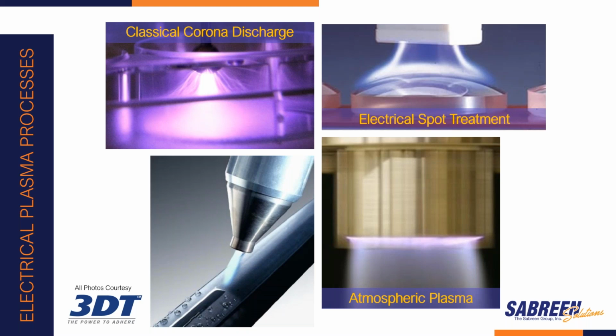Next, on electrical air plasma, it's a corona discharge spot treatment. In this method, the head consists of two hook electrodes in close proximity to each other connected to a high voltage transformer generating an electric arc of approximately 7 to 12 kV, but at lower frequency, 50 to 60 cycles. Then, using forced air, a continuous electrode arc produces a corona discharge or plasma. No positive ground is needed. In this process, virtually no cleaning capabilities are performed and ozone is produced.